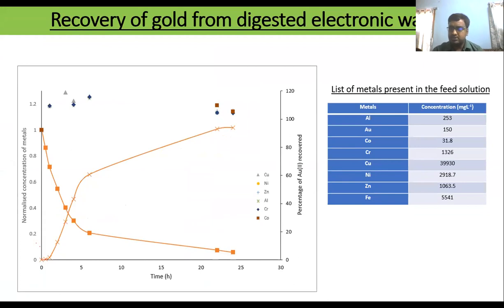And we got the metals present. So you can see the gold is around 150 ppm, but other metals like copper and nickel are present in very high amounts. But the good part is that this membrane selectively recovers gold. So you can see the concentration of the other metal ions remains almost the same within the membrane, but the gold concentration decreased.